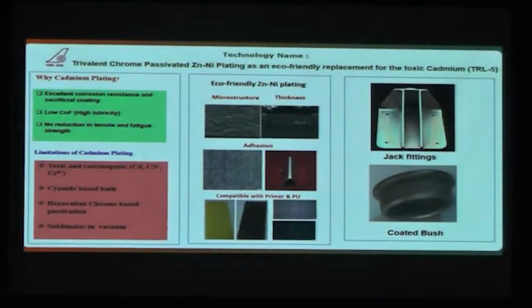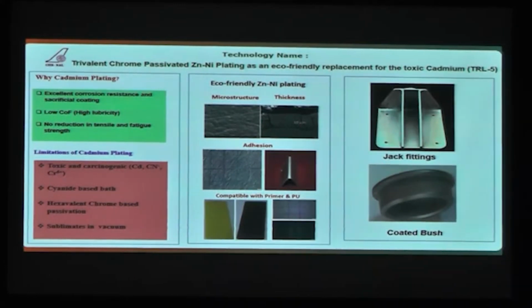The second eco-friendly technology which I would be talking about is the zinc-nickel process. It has been developed as an alternative to cadmium. Cadmium coatings are generally used for corrosion protection of high-strength steels because of their excellent corrosion resistance. They provide protection through a sacrificial coating, and have a very low coefficient of friction, that means high lubricity, and do not result in any reduction in tensile or fatigue strength.